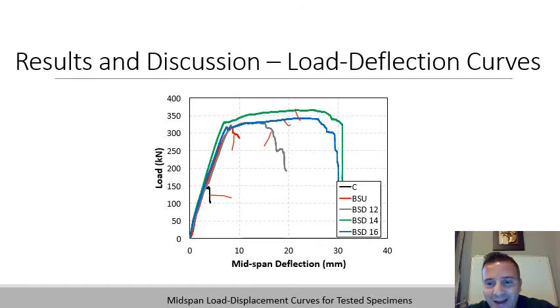So anchoring the ends of the sheets by splay anchors, a very simple method, will enhance not only the strength, it will also enhance the ductility. And you can see here that with the 14, there is no direct relationship between increasing the diameter of the anchor and the strength. Why is that? Because you are increasing the size of the hole, so that will maybe reduce the strength of your specimens. So basically we find that the 14 millimeter diameter dowel is going to be the optimum for this structure.